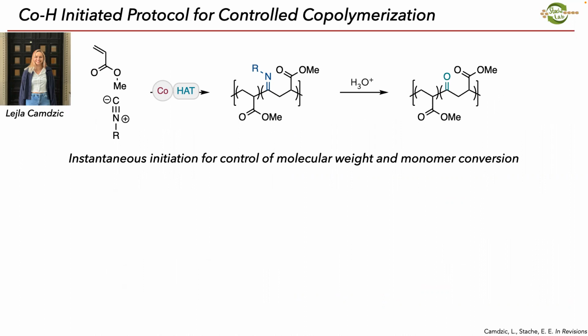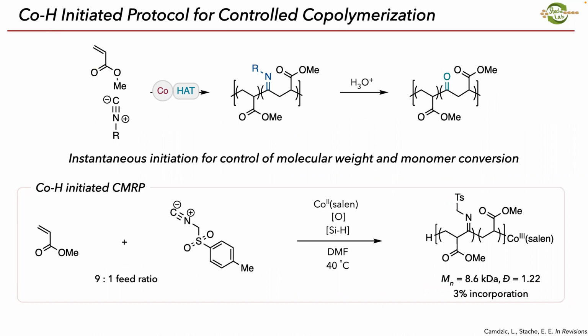So this is Layla, I didn't show her picture before, but now using this protocol that Sajad developed, she observed a very well-controlled polymerization. So now we have predictable molecular weight. We programmed in for 8.6, and that's what we see. And now we have low dispersities as well, so 1.2, with, again, controlled incorporation, 3%.